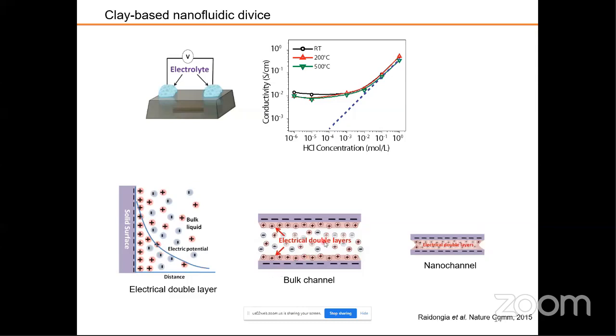Now, everything has a Debye length, but when the channels are very big, the Debye length is small. The properties of the material are determined by the bulk of the material, so the nature of the Debye length will be insignificant. But when you make nanochannels, both these surfaces come so close to each other that the Debye layers overlap. Now, the properties of the channels will be mainly determined by the nature of the electrical double layer, because it is not affecting the bulk solution. That is why in this region the conductivity is not changing. Even though we are changing the concentration outside, the inside concentration is determined by the electrical double layer of the walls. So it has formed a nanofluidic channel. That is why the conductivity is not changing with changing concentration of the reservoirs.